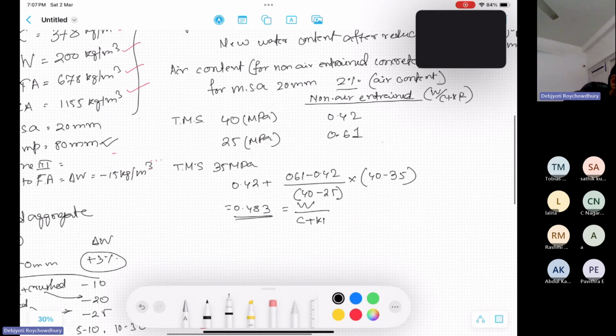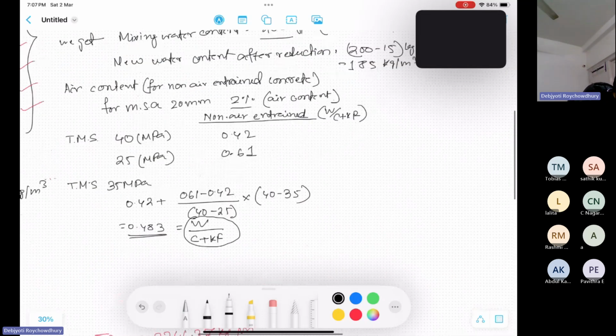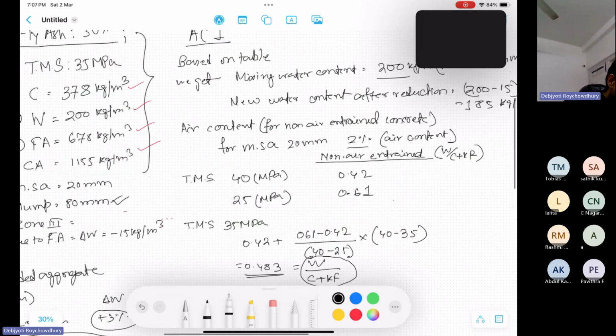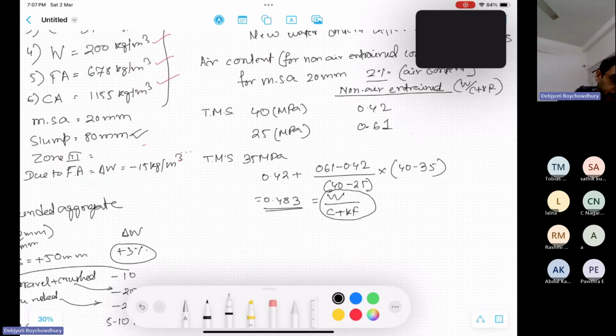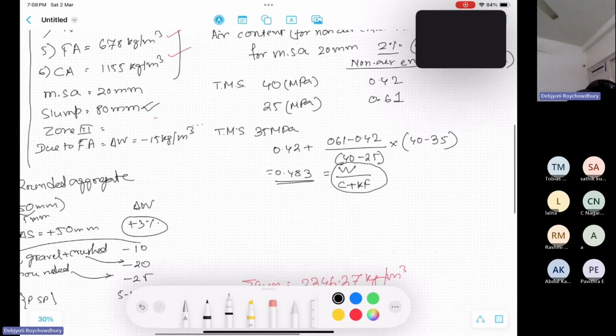This is water by cement plus kF, because here not only cement is there, the fly ash is also there. We have already calculated the water, the fly ash content and the cement content in our previous calculation. The new cement content C dash is 291.06 kg per meter cube, and the fly ash content is 124.74 kg per meter cube.